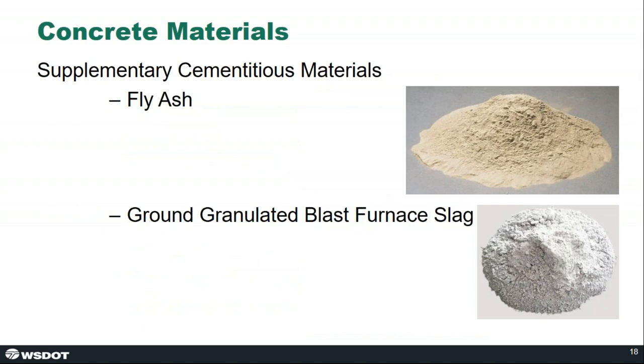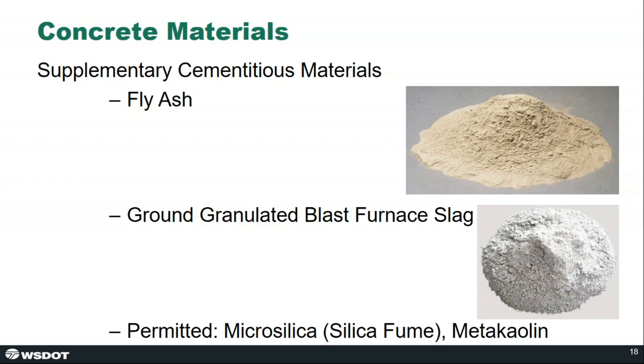Our bridge decks often include a fair amount of supplementary cementitious materials. Fly ash and slag are the most common. I think that's probably common throughout the country as well. These help control the cost of concrete, but also seek to reduce the permeability of the concrete. And per our specification, we also allow the use of microsilica or silica fume and metakaolin, another type of pozzolan. These materials are permitted, but we rarely see them proposed by our ready mix suppliers.